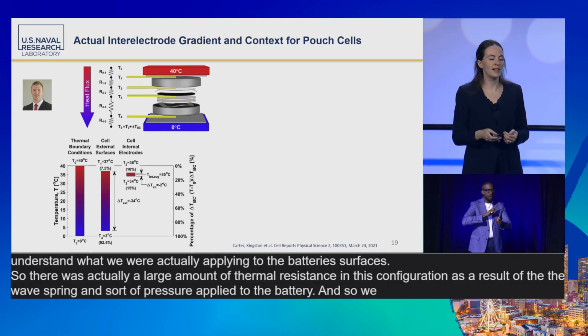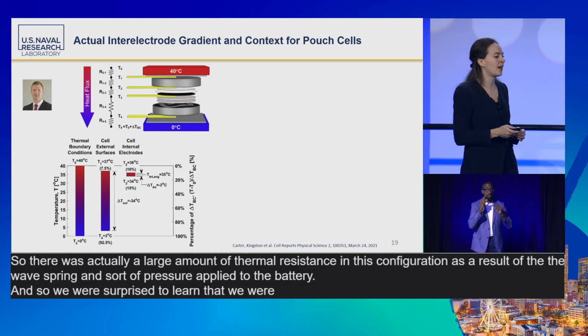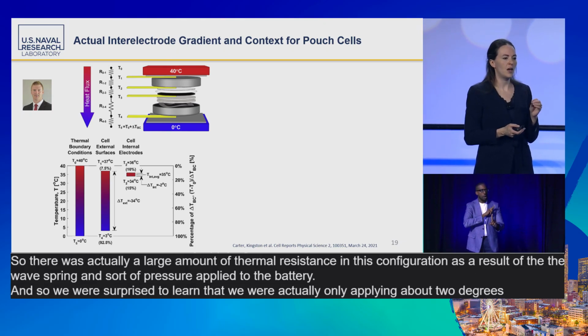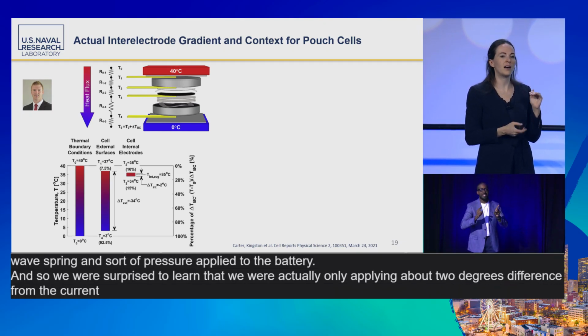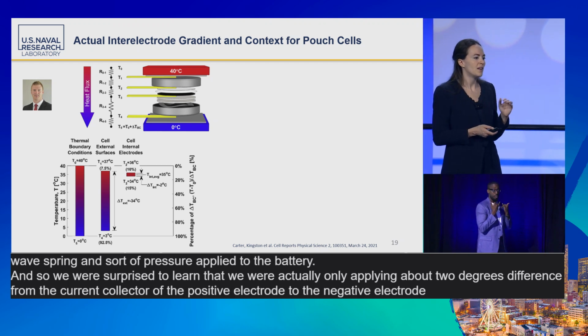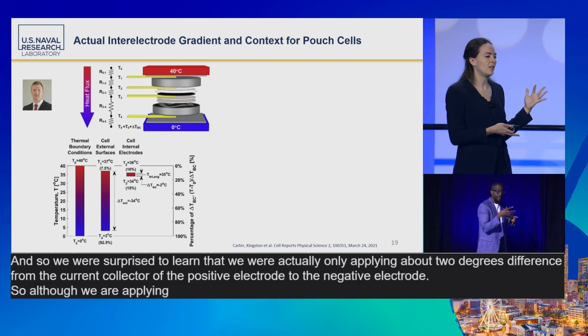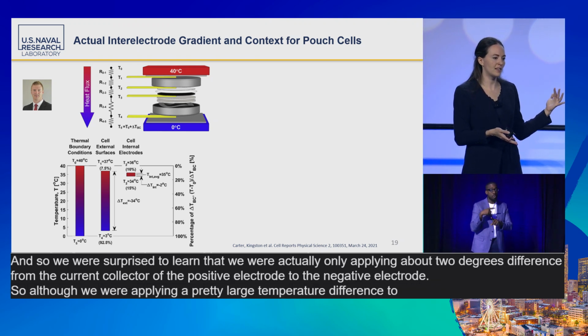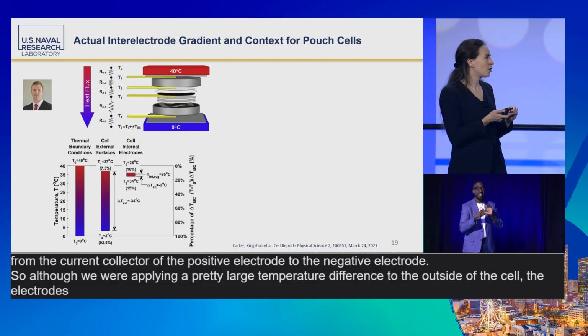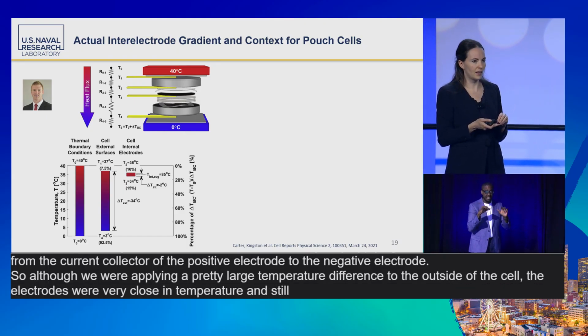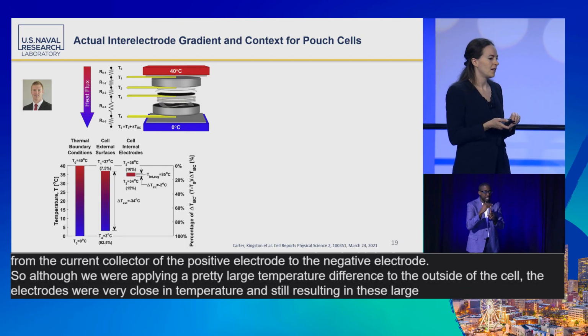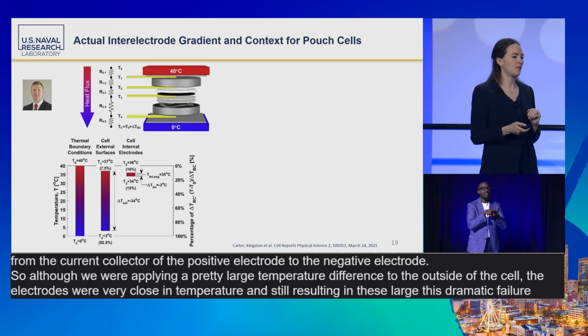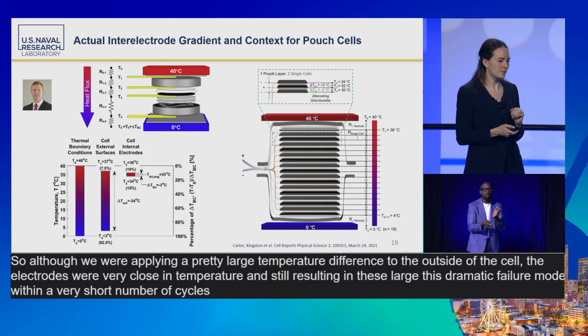We were surprised to learn that we were actually only applying about 2 degrees difference from the current collector of the positive electrode to the negative electrode. So although we were applying a pretty large temperature difference to the outside of the cell, the electrodes were very close in temperature and still resulting in this dramatic failure mode within a very short number of cycles.